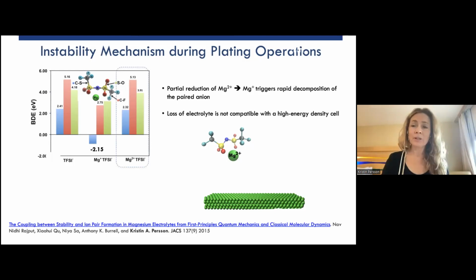However, if you assume that when magnesium needs to plate, it needs 2 electrons, and it's unlikely that those 2 electrons come at exactly the same time for every single magnesium that needs to plate, there should be some statistical variation of when they come. There should be some population of magnesium 1+. And we can calculate that, we can literally add an electron to the magnesium and see what happens to the TFSI. And this is the graph in the middle there, which shows that the CS bond, one of those unique bonds, now becomes quite exothermic. It really wants to break.